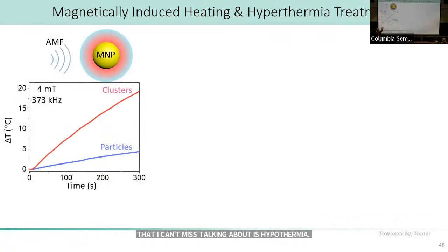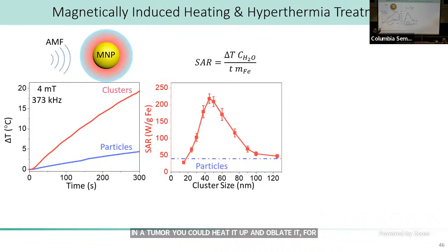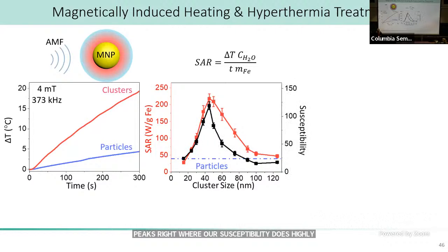Another application that I can't miss talking about is hyperthermia. One of the things I mentioned at the beginning is, of course, the concept that a magnetic nanoparticle, when subjected to an oscillating field, will heat up. And that's actually a really cool idea, and it's been used in some phenomenal ways. If you can put nanoparticles all in a tumor, you can heat it up and ablate it, for example. Same idea as photothermal ablation. The figure of merit for this system would be something called the specific absorption rate, which is how well you absorb that oscillating field and translate it into a delta T. And as we expected, what I'm showing you here is, as a function of cluster size, you see a peak in that effectiveness that really peaks right where our susceptibility does. So highly susceptible particles that are highly sensitive heat very efficiently. And it pretty much maps directly onto our measures of susceptibility over a range of different sizes.